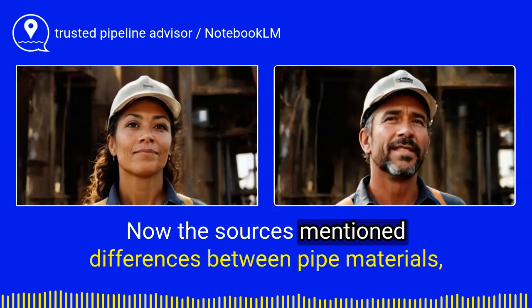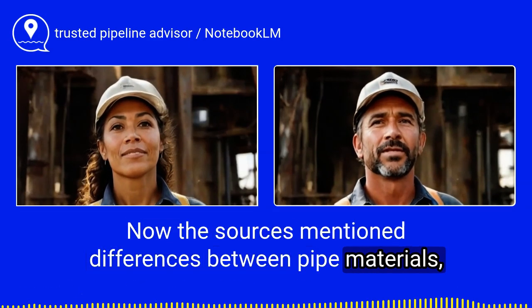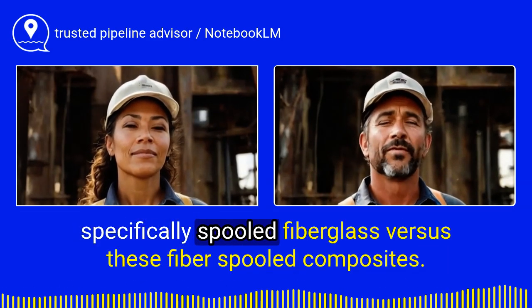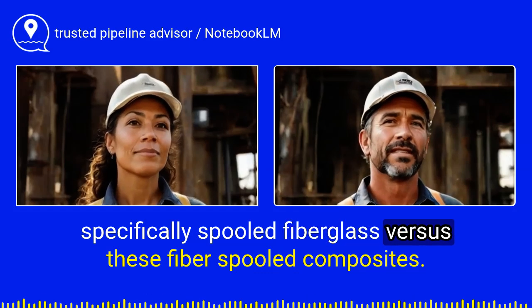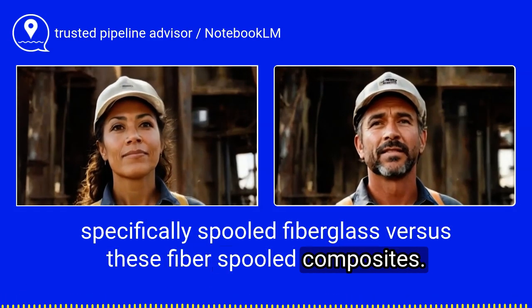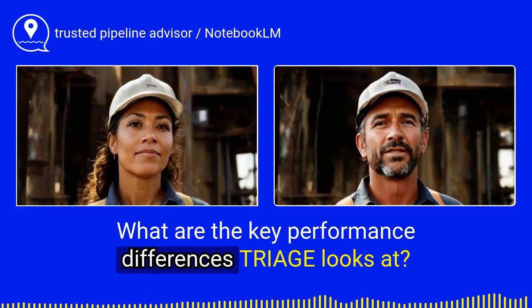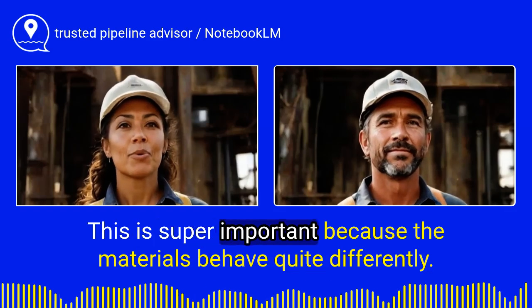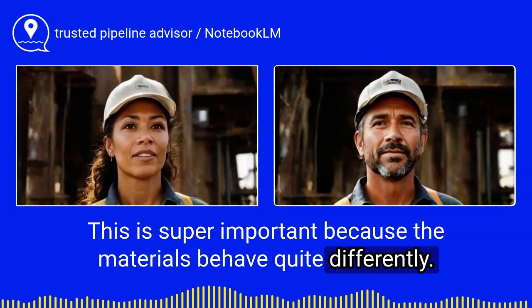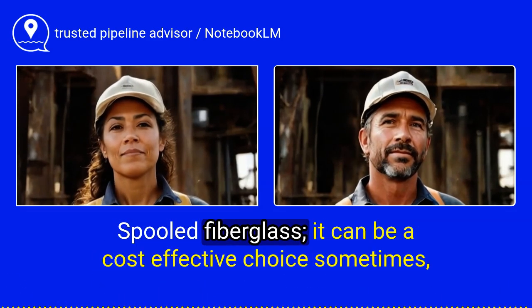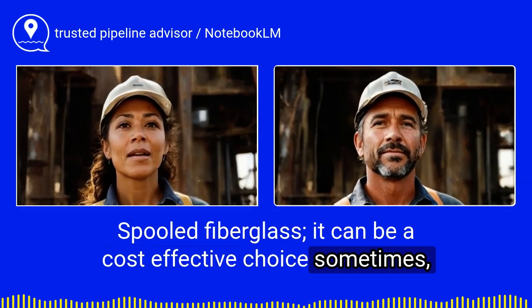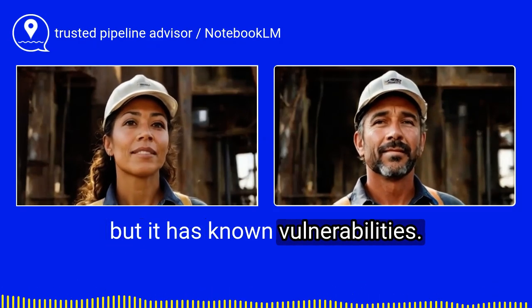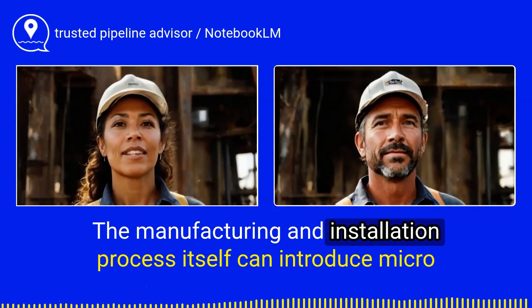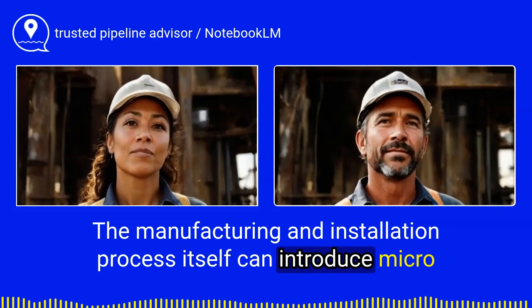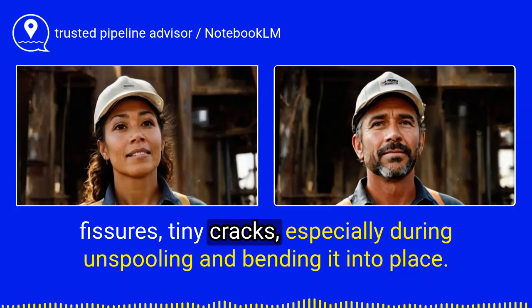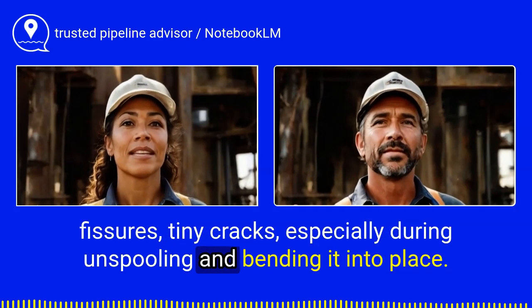Now, the sources mention differences between pipe materials, specifically spooled fiberglass versus these fiber-spooled composites. What are the key performance differences triage looks at? This is super important because the materials behave quite differently. Spooled fiberglass can be a cost-effective choice sometimes, but it has known vulnerabilities. The manufacturing and installation process itself can introduce micro fissures, tiny cracks, especially during unspooling and bending it into place.